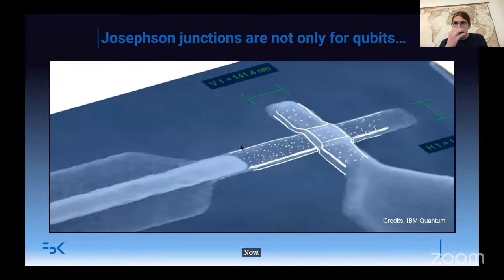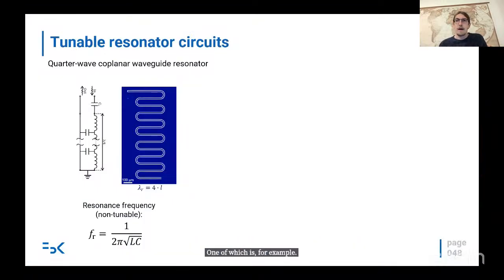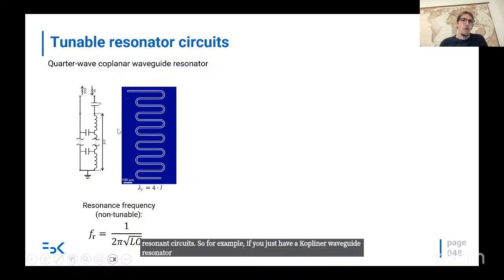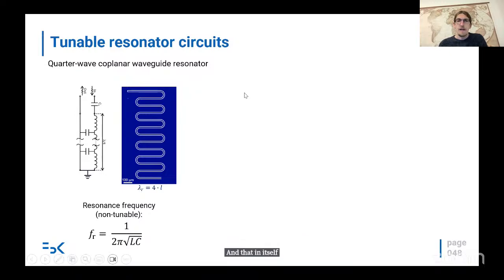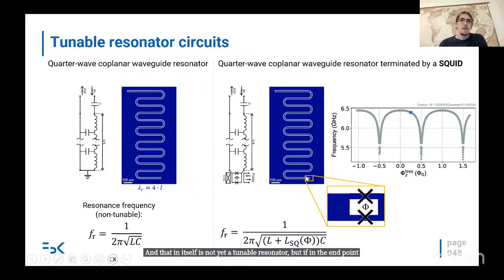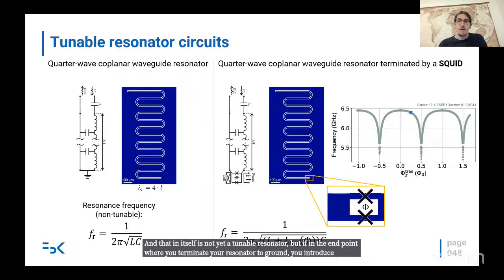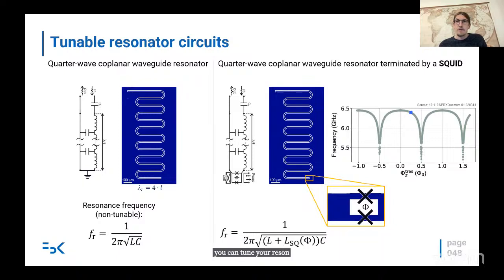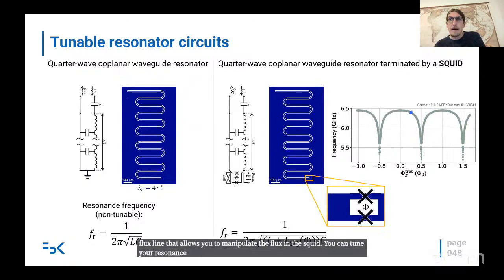Now, Josephson junctions, you can use them for qubits, obviously, but of course there are many, many other applications. One of which is, for example, if you want to make tunable resonant circuits. If you just have a coplanar waveguide resonator, which is simply a piece of coplanar waveguide terminated to ground, you will have a standing wave in here, a quarter wave, and that in itself is not yet a tunable resonator. But if in the endpoint where you terminate your resonator to ground, you introduce, for example, two parallel Josephson junctions forming a squid loop, you can tune your resonator as a function of the flux in the squid. So if you have a close by flux line that allows you to manipulate the flux in the squid, you can tune your resonance frequency, which has multiple applications.